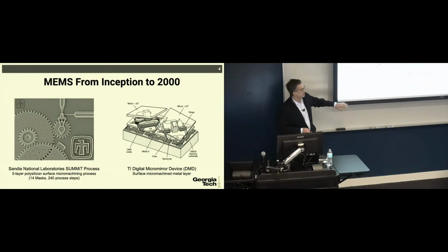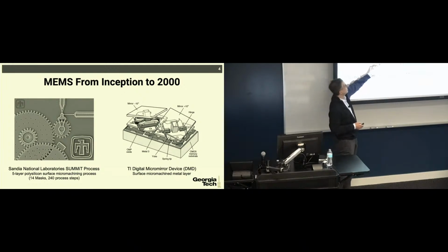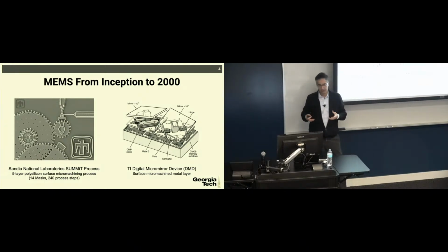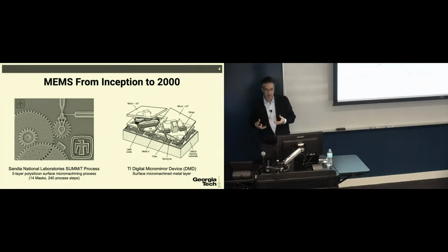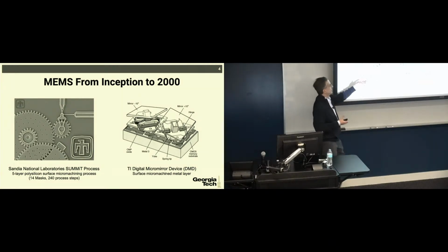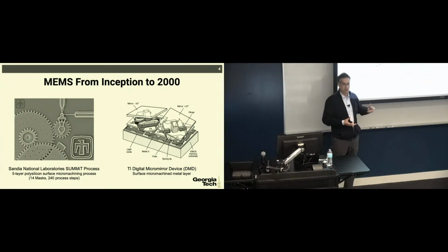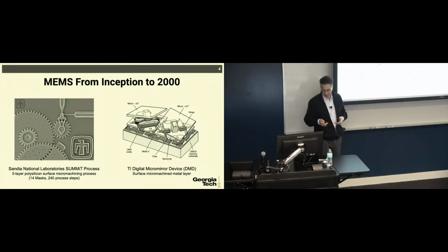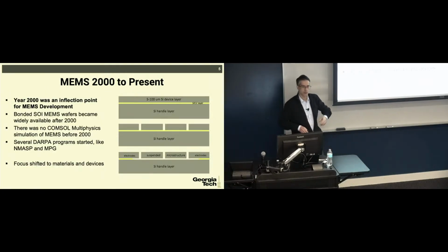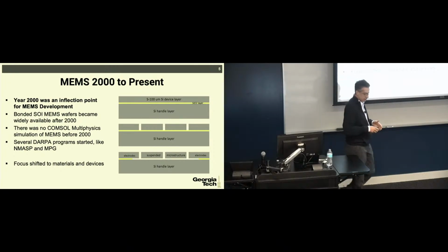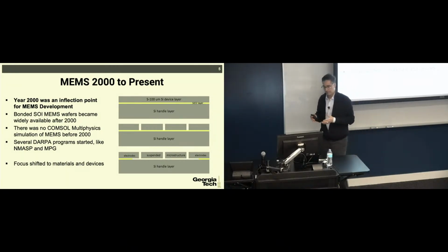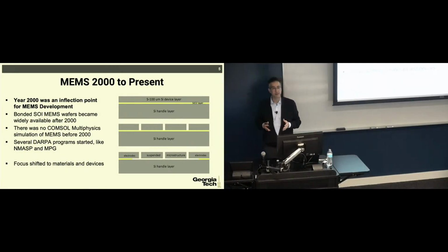The reason was that most of the mechanical devices, if you are really trying to get a mechanical action out of it, you have to use a little bit more mass. So these surface micromachine devices didn't have enough mass. So what happened at 2000 was that there was enough advances in the wafer bonding technology and grinding wafers that enabled introduction of the silicon on insulator wafers, okay?